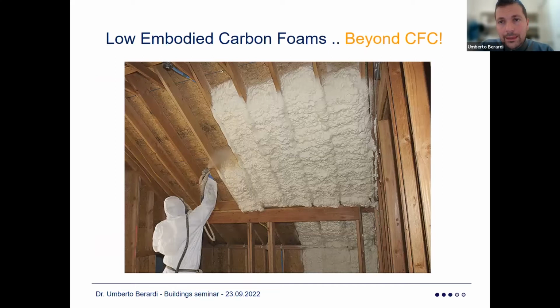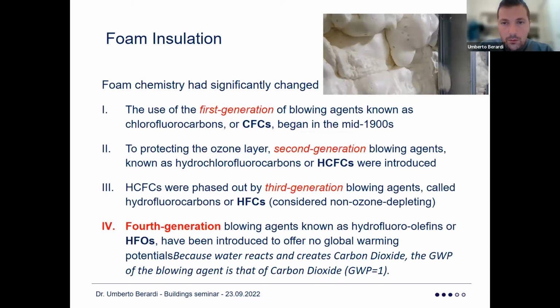Now I'm going to move towards another insulating product, but it's no longer aerogel, it's low embodied carbon foams. This interest comes from the fact that foams, in North America, because of the air tightness requirement, are a significant portion of the insulating industry. And the reality is that this industry has been affected by the critical role that CFCs have played on the atmosphere and the ozone layer. So, after the Montreal Protocol, we started looking at alternative ways to get rid of the CFCs because they were creating a lot of trouble.